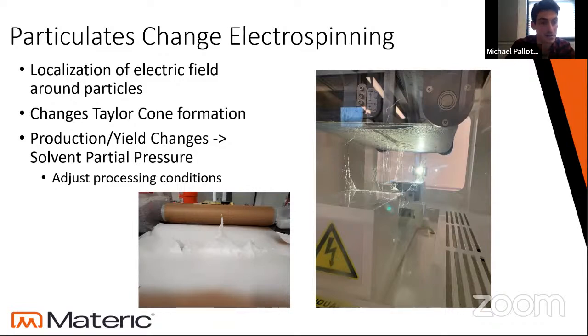And then finally, the production yield changes and the solvent partial pressures. We added these two pictures because we had done a number of iterations where we saw what we call bundles forming on the final nanofiber mat we were creating, because the additives were changing how the polymer solution interacted with the environmental conditions inside the electrospinning chamber. We found that we would have to adjust the humidity and temperature because the nanoparticles we added were changing the overall solution in a way that it either absorbed more water out of the air or was more easily impacted by the temperature inside the electrospinning chamber.